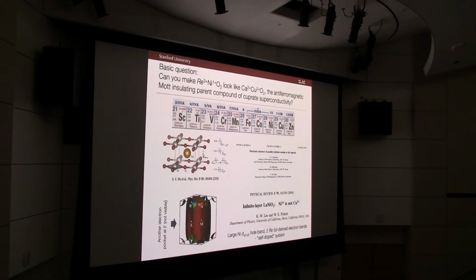So what is the basic idea or question in this framework? Which is, can you make layered nickelates to have the same layered crystallographic structure and electronic structure as found in the cuprates? And so I just gave this direct analogy to the so-called infinite layer cuprate, which is the antiferromagnetic insulating parent compound of cuprate superconductivity.